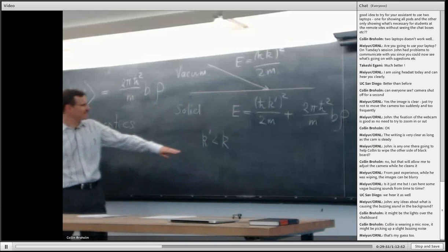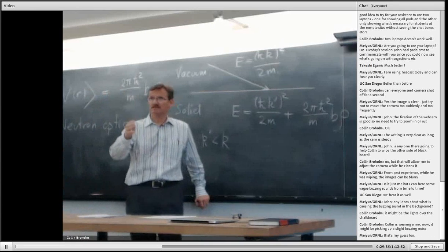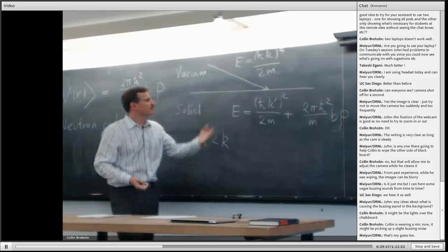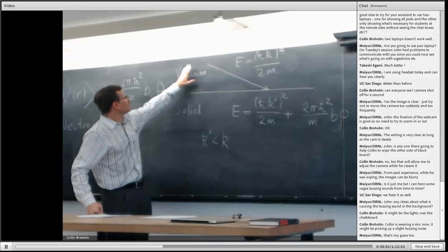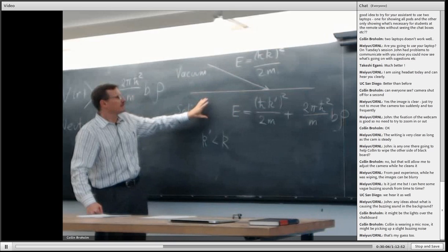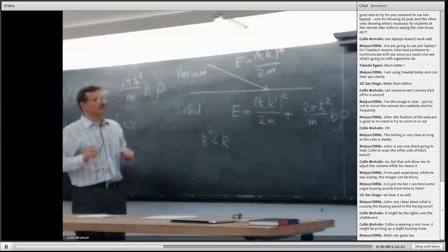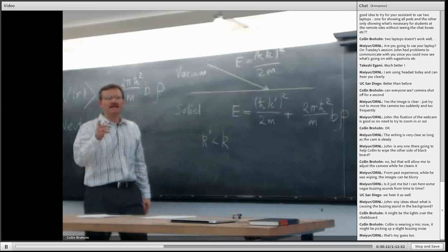And this is quite interesting because that's exactly the opposite of what happens in optics, so with photons. In regular optics with light, if you go from a vacuum to a denser optical medium, then you're going to find that the wave vector becomes longer in the denser medium, and that corresponds to an index of refraction.